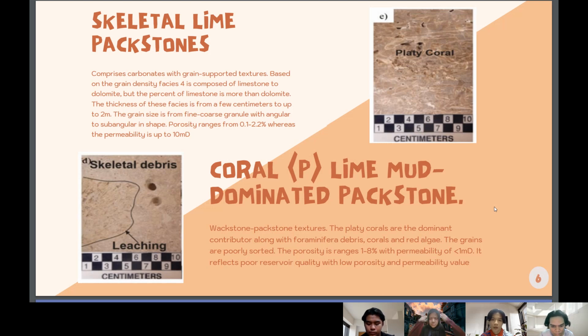And the last one is coral lime mud dominated packstone. This facies has wackestone textures, and the platy corals are the dominant contributor along with foraminifera debris, corals, and also red algae. The grains are poorly sorted, and the porosity ranges from 1 to 8% with permeability of less than 1 md. It reflects that this type of facies is of poor reservoir quality with low porosity and permeability values.